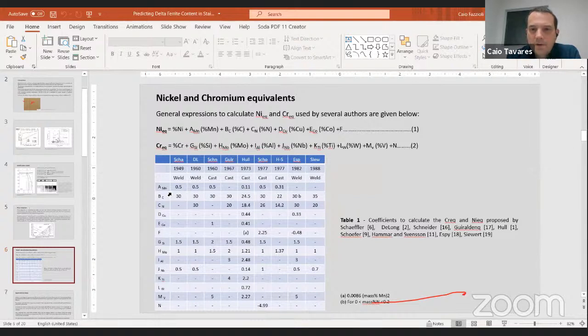You see here on the formulas, the amount of manganese is considered as nickel equivalent. So in fact, those elements that are represented as nickel equivalent are elements that are austenitizers. They create austenite in the microstructure. And those in the chromium equivalent are elements that generate ferrite in the microstructure. So in the case of manganese, you just have to input the amount of manganese in this calculation, and then you get the right prediction of the ferrite.